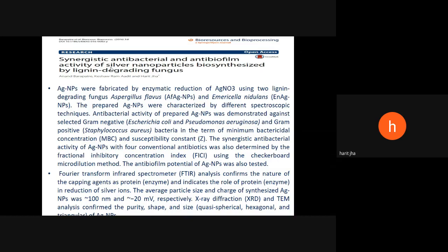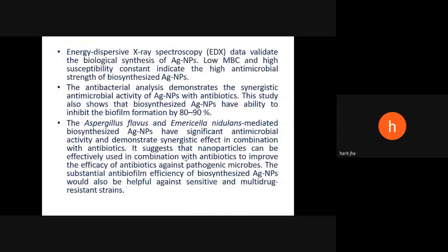The FTIR confirmed the nature of the capping agent as protein and indicates the role of protein, that is the enzyme, in reduction of silver ion. The average particle size and charge of the synthesized silver nanoparticles were 100 nanometer and 20 millivolt respectively. The XRD and TEM also confirm the purity, shape, and size of the silver nanoparticles. The EDX data was used to validate the biological synthesis of silver nanoparticles, and the low MBC and high susceptibility constant indicated high antimicrobial strength of these nanoparticles.